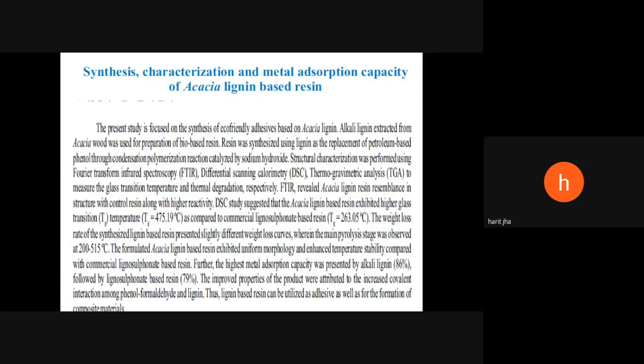Further, the highest metal adsorption capacity was presented by the alkali lignin, up to 86%, followed by lignosulfonate based resin. The improved property of the product was attributed to the increased covalent interaction between phenol, formaldehyde, and lignin. This lignin based resin thus can be utilized as an adhesive as well as for the formation of composite material.